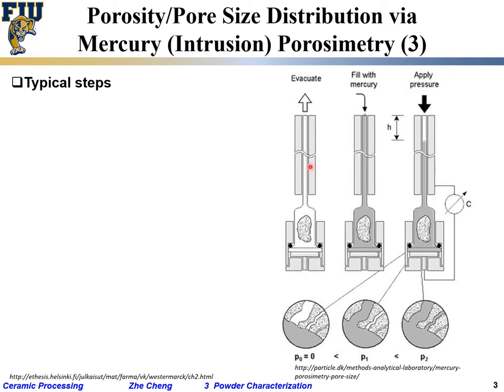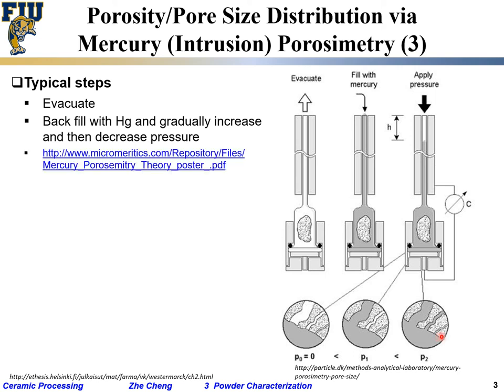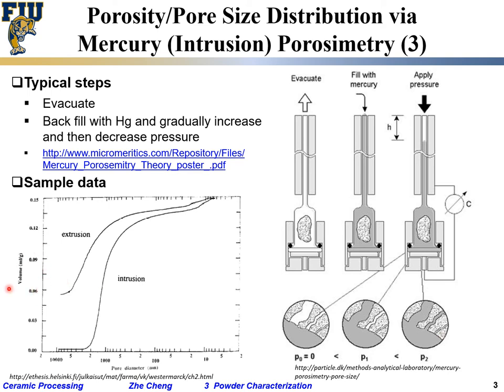In the experiment, you have a sample in a tube. First you evacuate to create a vacuum, then backfill with mercury and gradually step up the pressure. When pressure is low, you fill the pores with larger radius first. As you step up from P1 to P2 with higher pressure, smaller pores gradually get filled. The sample data shows volume versus pore diameter: starting from larger pores and progressively filling smaller and smaller pores, for both intrusion and extrusion.